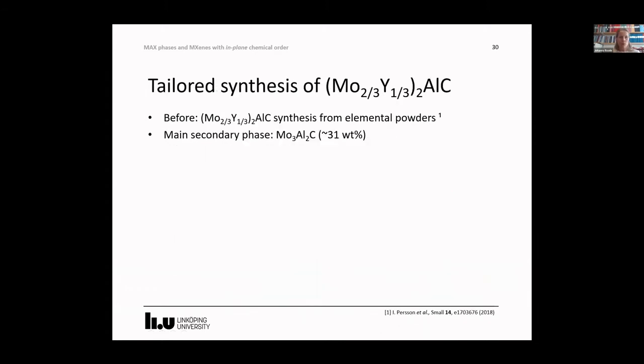So as I mentioned before, we synthesized this i-MAX from elemental powders before. This worked all right. The most important thing is to make sure that your yttrium is not too old, since it tends to oxidize. But still, what we could not get rid of is this secondary phase, which was more than 30% of the sample, even after optimization of the synthesis conditions.